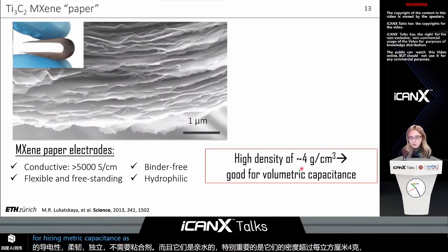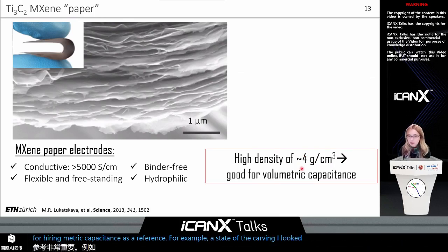As a reference, for example, the density of state-of-the-art carbon electrodes is much less than 1, typically in the range of 0.3 to 0.5 gram per cubic centimeter.